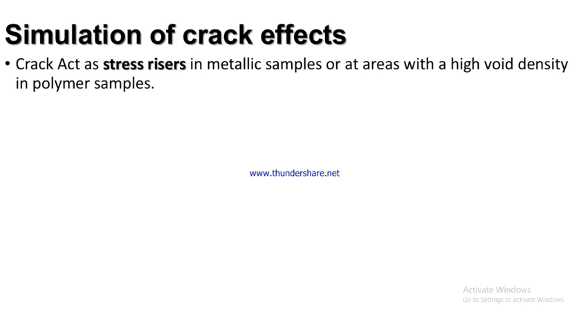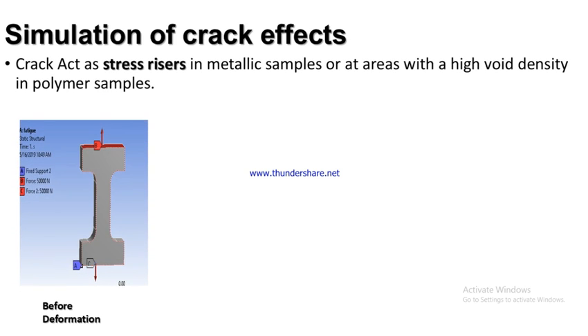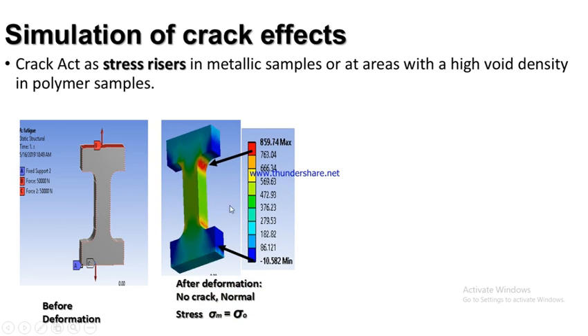So I did a little model in order to simulate what we call the stress concentration, the stress amplifying factor, in materials. This is a component which was subjected to tensile stresses, 50,000 newtons, which is 50 kilonewtons, on the y-axis, opposite to each other. When this material was pulled in tension, this is the result we had, and we found out that the stresses are basically concentrated at the fillet parts of the material, which are at this joint, at this point.